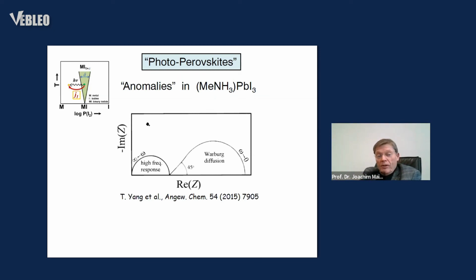or in terms of impedance spectroscopy, you do not only see a normal response, which gives you the total resistance here, but there is then this phenomenon at low frequencies, which comes from blocking, so that at 0 frequency, you only measure the electrons that can go through the electrodes. And this material has quite a high ion conductivity, so this can be very different from this one here. And it takes a while.